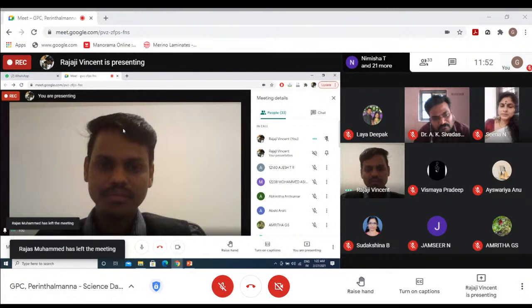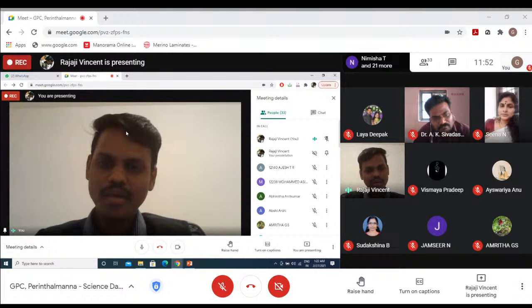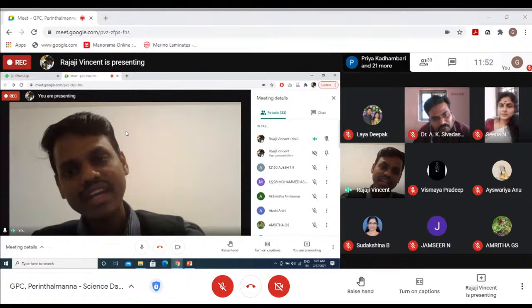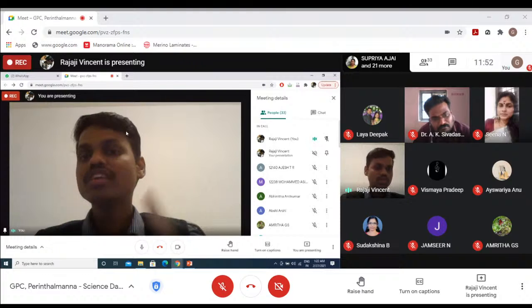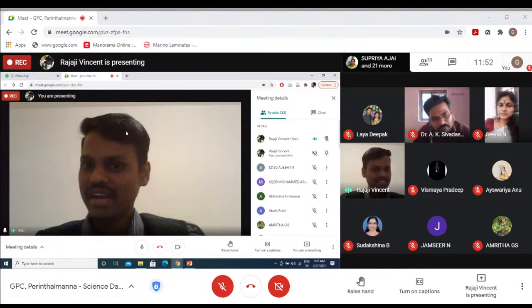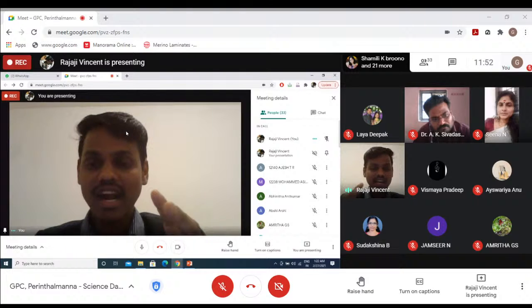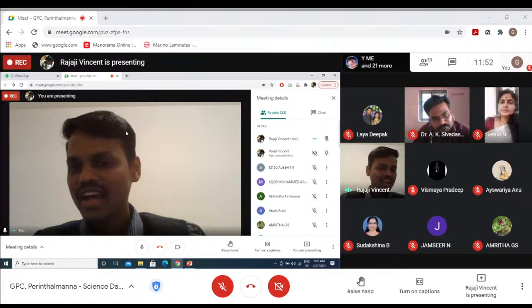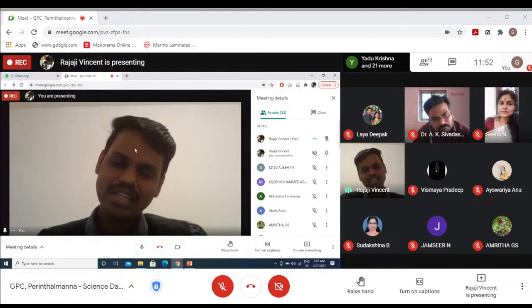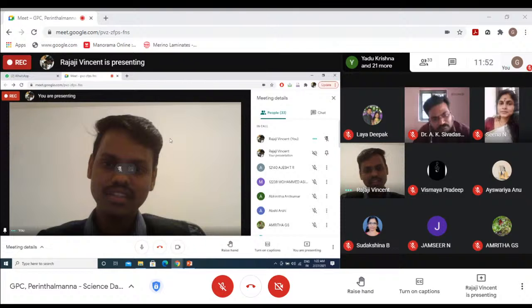But I have done one exercise using Raman. I was given a titanium oxide, a white powder. We did a Raman, but we did not have much understanding. Then we did EDX, which told us titanium and oxygen are present in the system in a 1:2 ratio. Then we got to know it was titanium oxide. Titanium oxide has 3 kinds of phases: anatase, brookite, and rutile. So we compared the 3 phases. The 3 have different symmetry, and one symmetry matched ours. So we identified our unknown sample. This was an exercise we did in 2013.